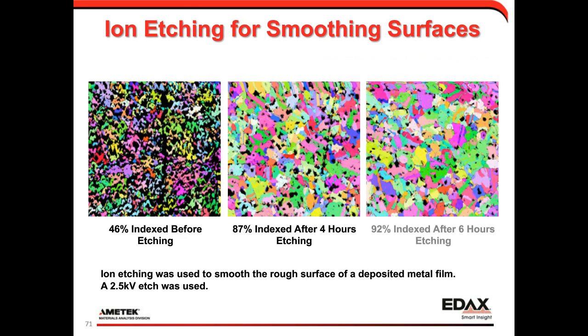This is an example of a cadmium telluride solar cell. So when this is first deposited, there's some significant topography. We can see that on the right. The black areas are areas where the beam's blocked. So again, we went in at an almost grazing angle, about a 10-degree grazing angle with a 2.5 kV broad beam etch to sort of smooth out the surface. And you can see that our indexing rate went from below 50% to around 90% after some ion etching. The residual black areas there are pores in the film.